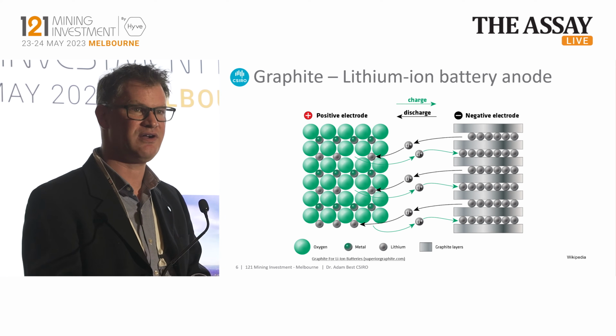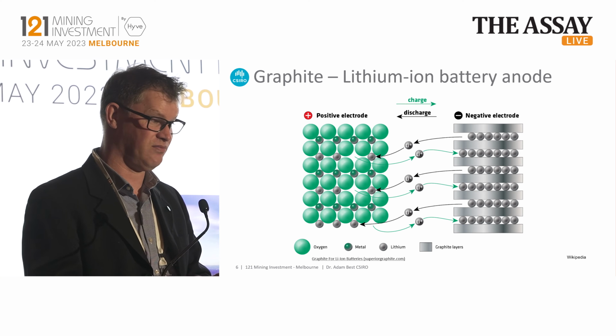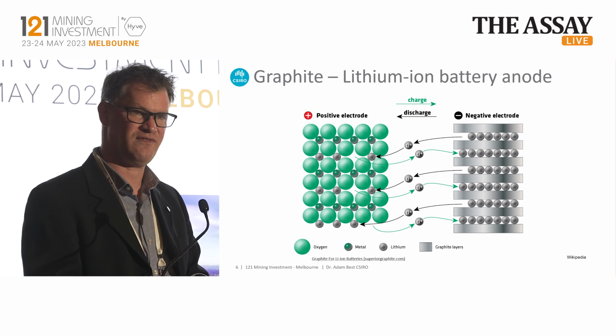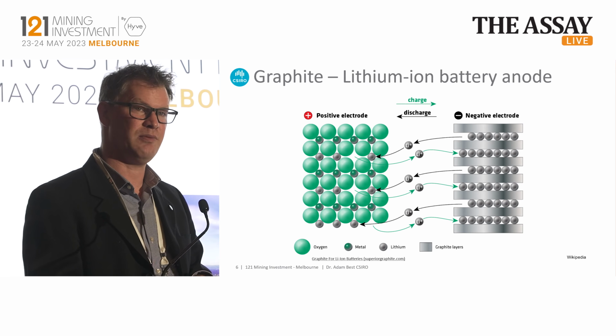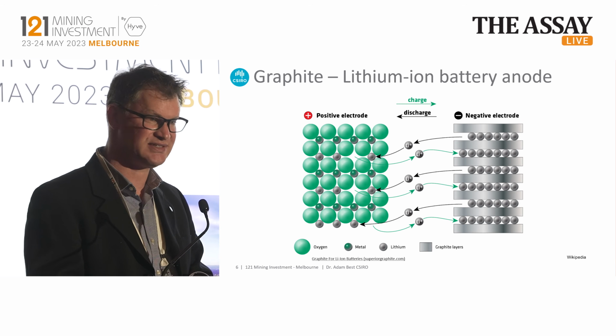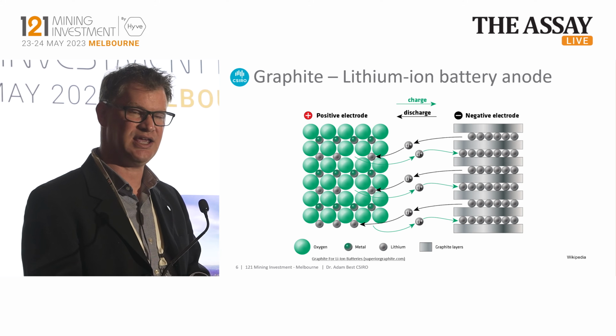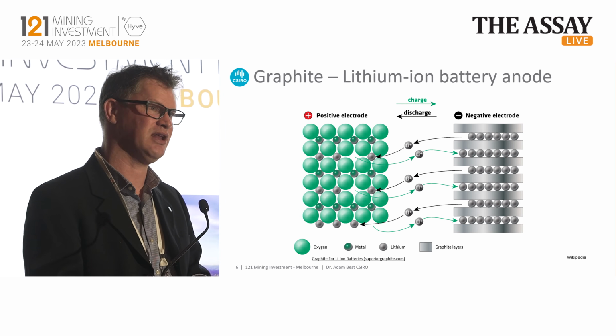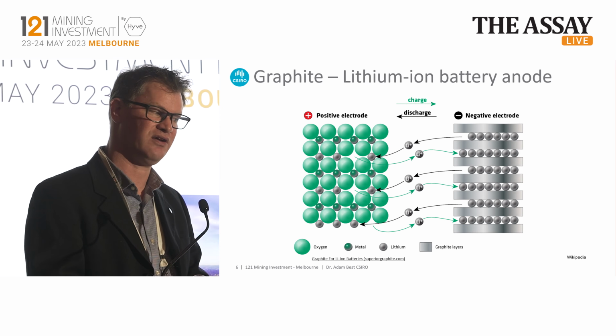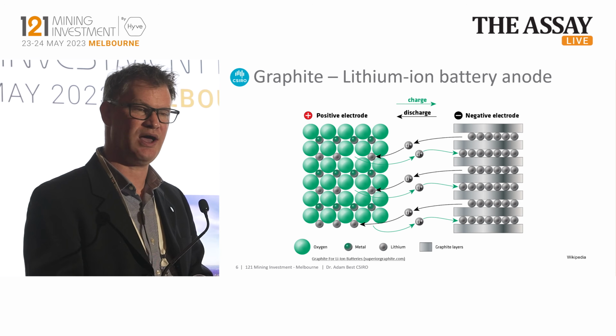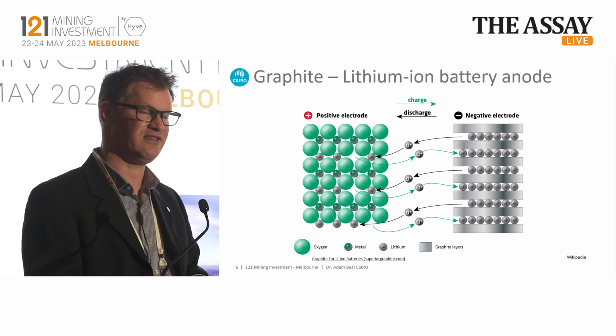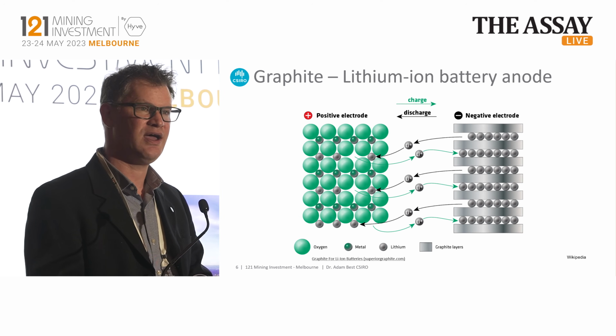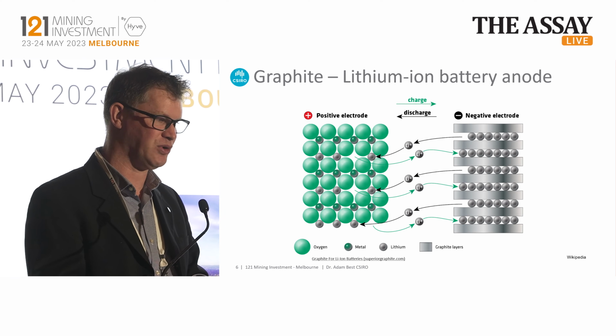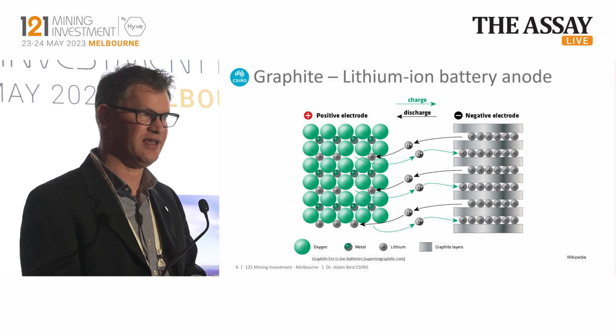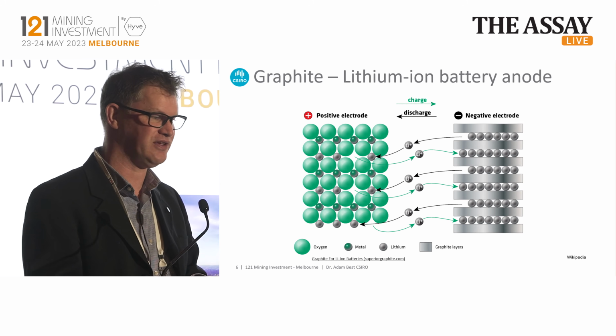And silicon is an emergent material in the marketplace, and this is because it has at least a factor of 10 higher storage capacity than graphite, but it has considerable challenges in terms of use. The other alternative is lithium metal, and that was where the initial lithium battery started, but there are substantial technical challenges in being able to plate and strip lithium in a reproducible manner for hundreds, even up to thousands of cycles. But also there's a supply chain challenge as well, is that there's not enough lithium metal available to actually supply the battery industry, and so there's a real need there to develop new technical solutions to actually break that bottleneck. So for this reason, graphite is the dominant anode material used in today's batteries.